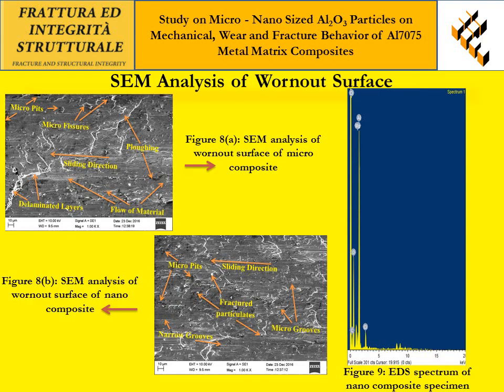Figures 8a and 8b show the worn out surface of composite and nanocomposite specimens. The SEM analysis of the worn out surfaces of the nanocomposite depicts the formation of narrow grooves with dark layers. Generally, this indicates that the nanocomposite exhibits improved wear resistance when compared to microcomposites.